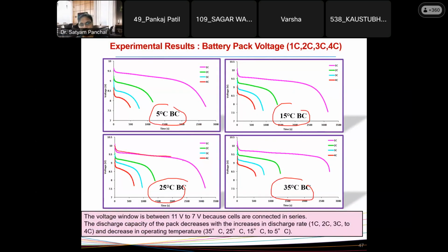So you can see over here at 1C discharge, you will see a little flat curve, then the 2C, 3C, and the 4C. So if you discharge the battery at higher current, you will see the drop in the voltage. So voltage window, as I said earlier, is between 11 to 7 volt because all cells are connected in series, and the discharge capacity of the pack decreases with increase in the discharge rate. So starting from 20 ampere meaning 1C all the way to 80 ampere meaning the 4C, and decrease in operating temperature starting from 35 all the way to 5 degrees centigrade.